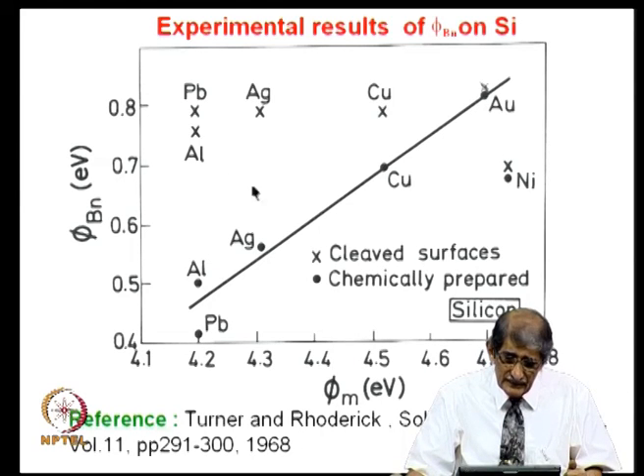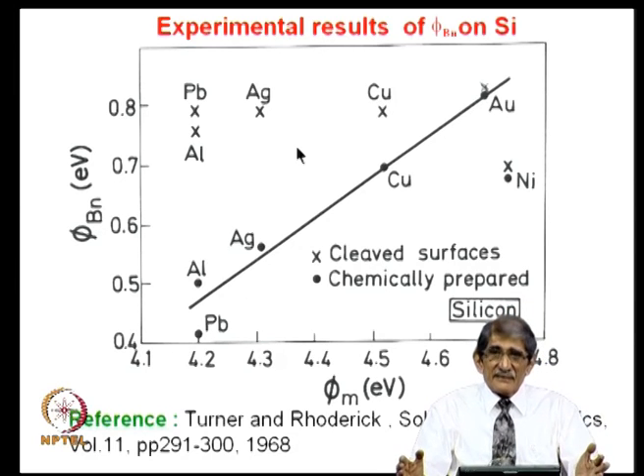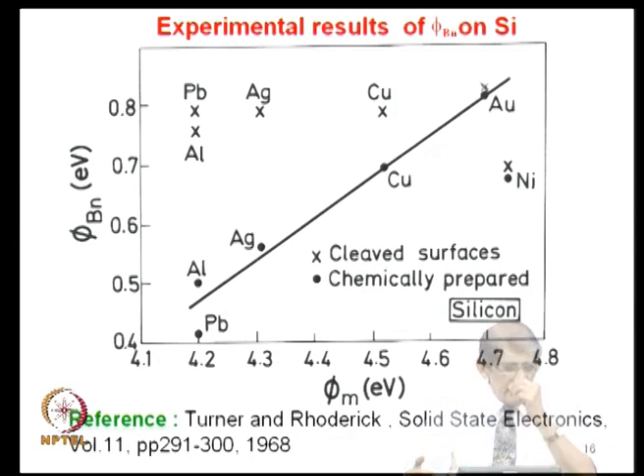Now, what they did was, let us cleave the surface and give a chemical treatment. For example, if you clean it with HCl H2O2 solution and ammonium hydroxide and H2O2 solution, then what you get will be a surface which has a layer of oxide. A thin layer of oxide will be there, even when you put it in an etchant like RCA1, RCA2, because of that H2O2 action, there will be some amount of oxide. It is a very, very thin layer, maybe less than a nanometer, a few angstroms, 1 nanometer is 10 angstroms, a couple of angstroms, that is sufficient. It passivates some of those dangling bonds.